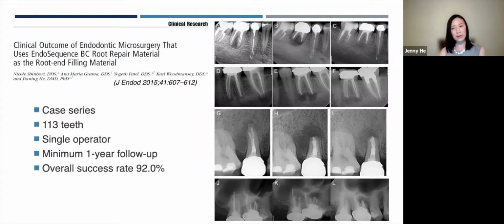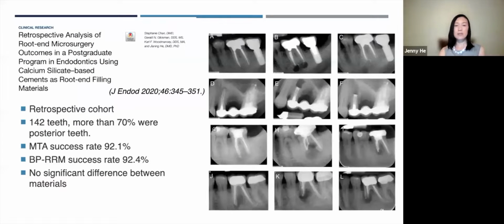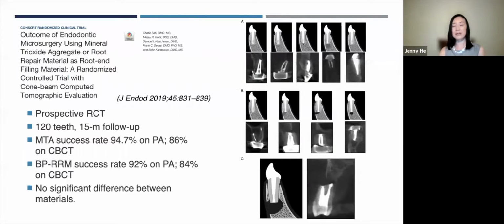And the second paper, if we can go to the next one, was based on cases treated by our residents at the dental school. So this study also included a control group where we used MTA as the root end filling material. And as you can see, there's virtually no difference in success rate between MTA and root repair material. So as you can see, even in the hands of less experienced residents, they were able to achieve a very predictable success using this material and this technique, because the materials and handling properties of the material allow us to greatly simplify the technique.